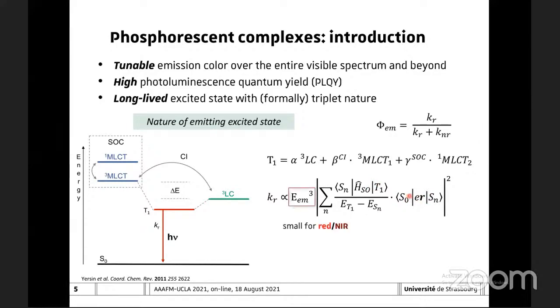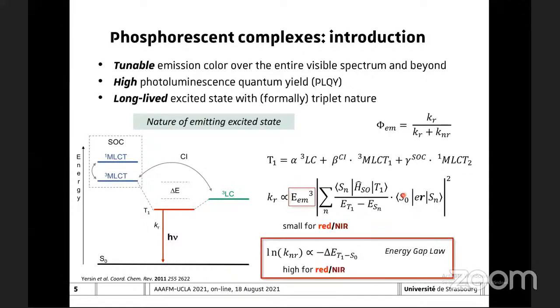So the problem is that the emission energy is intrinsically small for red and near infrared emitters, which brings to an intrinsically small radiative rate constant. On the other hand, there is also a second parameter that has to be taken into account, which is derived by the energy gap law, which is the non-radiative rate constant. In particular, the logarithm of the non-radiative rate constant scales with the negative of the difference between the triplet excited state and the ground state, which means that the non-radiative rate constant is typically high for red and near-infrared emitters.